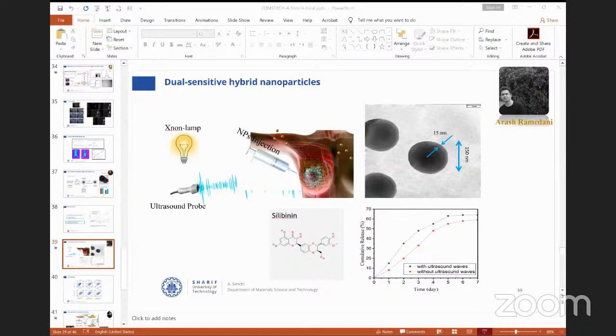As you see in the graph side, the release rate of the anti-cancer drug versus the time of the ultrasound. So she could successfully show that by ultrasonic wave, we can control the release rate.